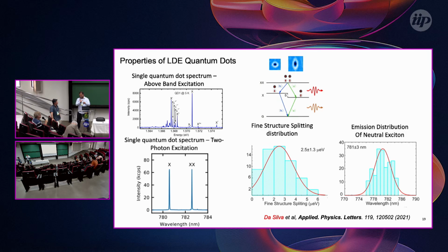This is coming from the confinement. If you have asymmetric confinement, this is the energy level we're splitting in two lines, in two levels. And you can measure this by polarization measurements. This is due to the geometry. In the case of gallium arsenide, it's because of the symmetry. If you have elongated quantum dots or nanoholes, this fine structure splitting will increase.